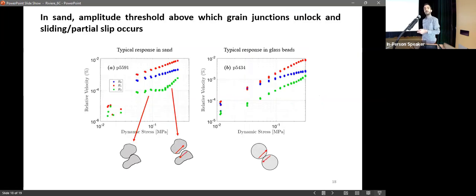Okay, and then one last observation that we have made is if we look at the nonlinear parameters as a function of the amplitude of the dynamic stress, we see that in glass beads on the right. I'm looking at this parameter R2, which is related to this curvature and the shearing of the contact. In glass beads, we see that R2 is increasing with dynamic stress in a monotonic fashion. But in sand, we see that R2 doesn't increase with stress until a certain amplitude, and then it starts to increase quite dramatically. What we think is happening here is that the grains are locked, and if you don't shake the sample enough, then they are going to remain locked, and R2 is not going to increase. It starts to increase only when you increase the amplitude of the oscillation.